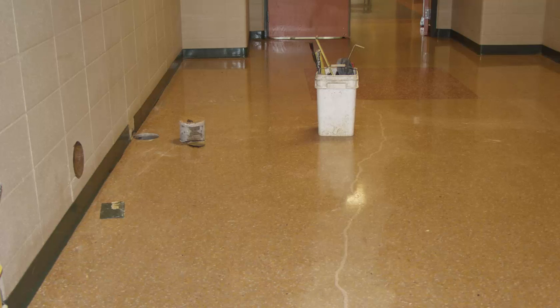A correctly proportioned mix design with a low water-cement ratio, properly sized and graded aggregate, welded wire reinforcement, and minimally spaced contraction jointing would have significantly reduced the cracks in the terrazzo in this photo, but this concrete had none of those.